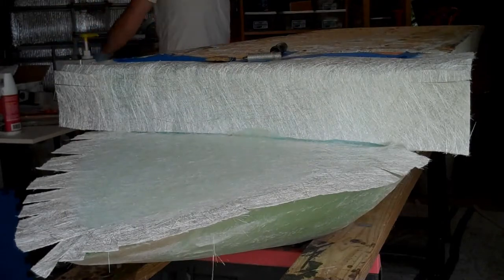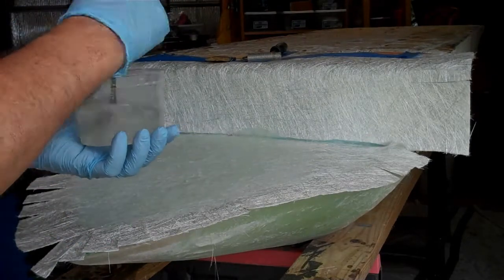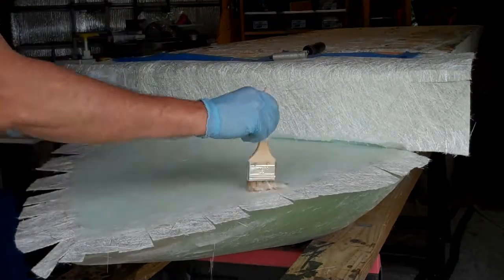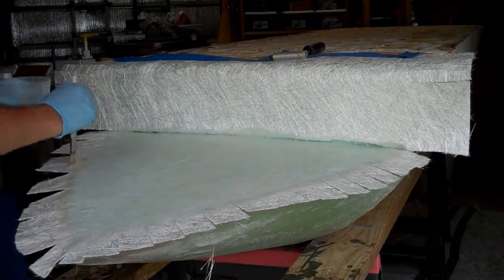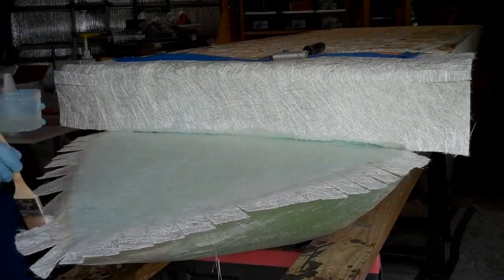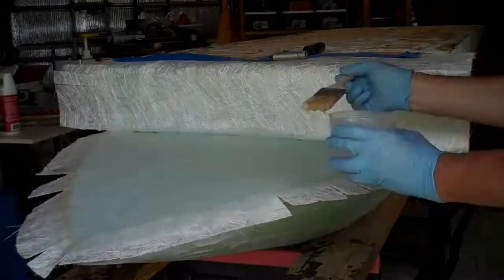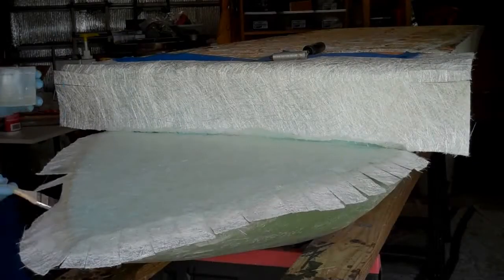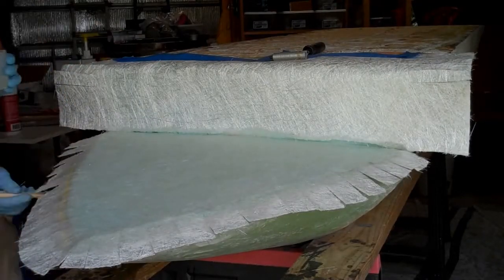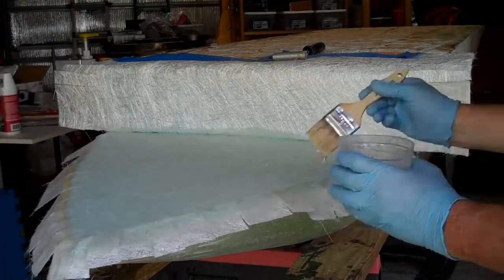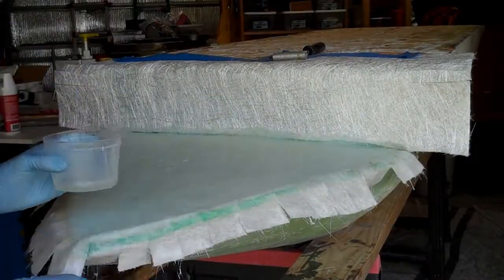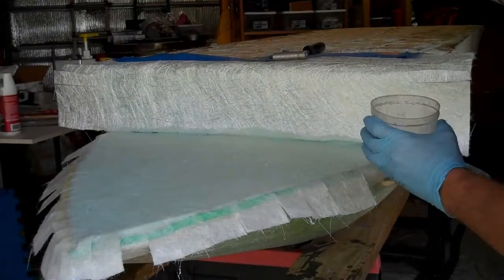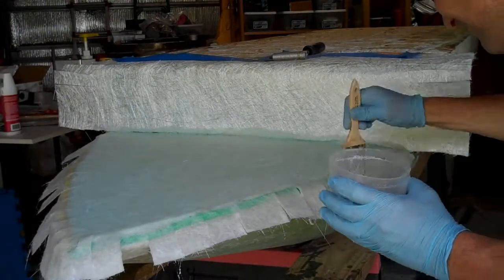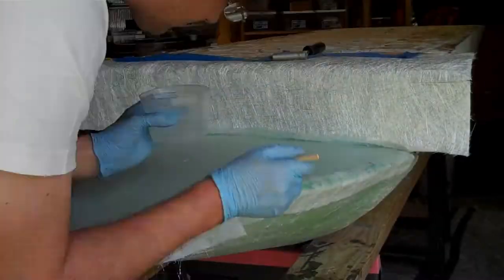Chop strand mat uses a lot more epoxy than woven fiberglass, so I'm mixing multiple batches as I go. I use a chip brush to gradually work my way around the edges, getting more and more epoxy resin on the cut tabs, while trying to keep as much as possible from falling onto the drop cloths on the floor. Once the fibers in the mat are fully wetted out, they bend and can be stuck to the bottom part of the pontoon. You know you have enough epoxy on them once they hold their shape and stay in place.